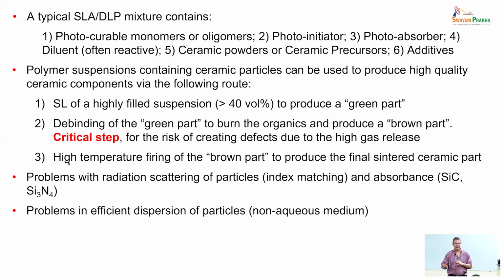But there are a lot of issues in terms of the size of the part that you can generate, typically a few hundred microns or a few millimeters in size. And you have issues with the fact that for two-photon polymerization, you're basically generating your part, writing inside a volume of liquid. And if you do that in a slurry that is flowable, what happens is that the part will move while you are printing because you change the density of the part and you will not be able to have a precise shape.